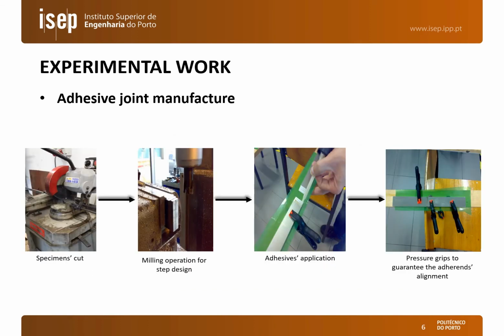Regarding the experimental procedure, we will begin with the fabrication of the specimens. First, we acquired bars with the final width of the specimens. We have to cut these bars. After that, we machined or milled the steps in a conventional milling machine. In the third figure, we can see the adhesive application. And finally, in the fourth figure, we can see one specimen already curing with pressure grips being applied so that the joint is in proper place for bonding.